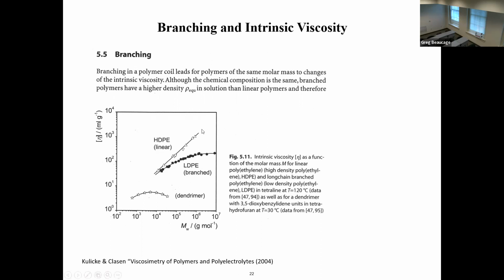So it gets even worse with dendrimers, which is what we're looking at this week. They have this weird behavior: they not only don't continue on a linear trend, or plateau, but actually drop at high molecular weight. This is called a peak behavior, right? You see the same kind of behavior for a different reason in polyelectrolytes. This would be a slope of 2 for a rod, and it's a rod because the charges are forcing the thing to line up. It's got a huge persistence.